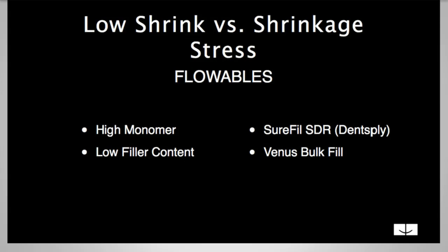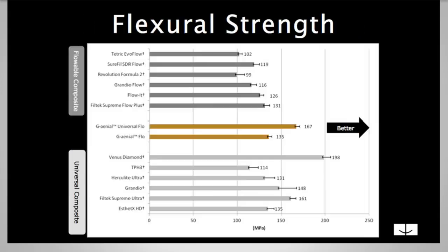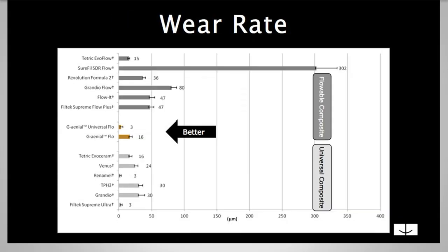But you cannot use SureFil on occlusal surfaces, anywhere that's going to have wear. It does not have a very low wear rate. And that's where G-aenial Universal Flo comes in, this new one by GC. Their flexural strength is very, very high. You can see higher than any of the flowables on the market, and it's higher than a lot of the universal composites on the market also. But the best thing about it is that the wear rate is very, very low. It's much closer to other packable composites. You can see here what I was talking about with SureFil SDR Flow. You can't put that on a surface where there's going to be function.